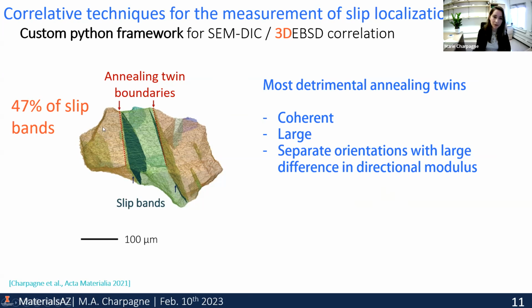We found that most slip bands actually form next to these twin boundaries, especially the ones that are coherent, that are very large, meaning if you have a very large twin plane area, and also the twin boundaries that separate orientations with a large difference in directional modulus with respect to the loading direction were actually the most detrimental. And by this, I mean the most intense slip bands were located nearby these twin boundaries. So that tells us where the weak link in pretty much any FCC material is. It's these coherent, large annealing twin boundaries that have this particular orientation in the material.